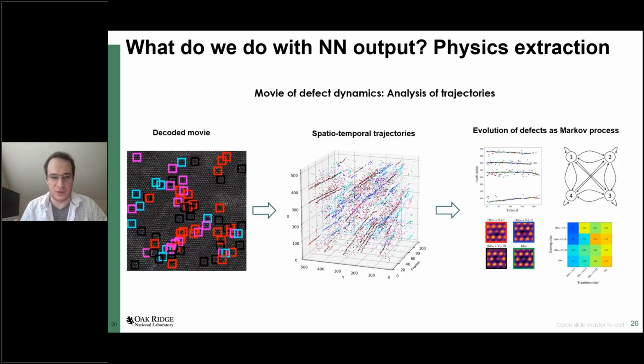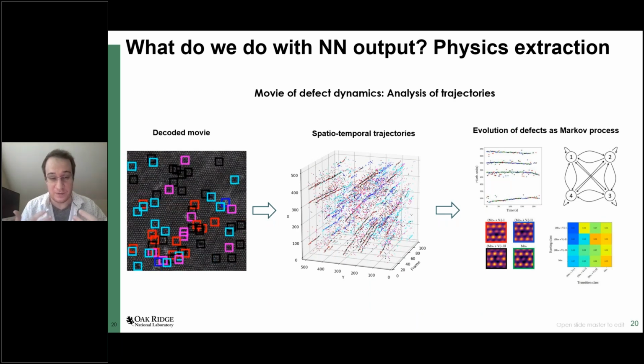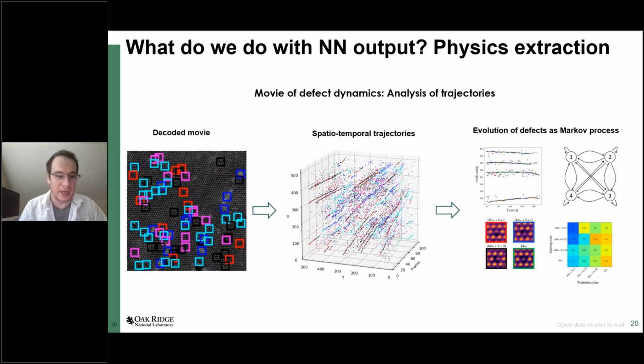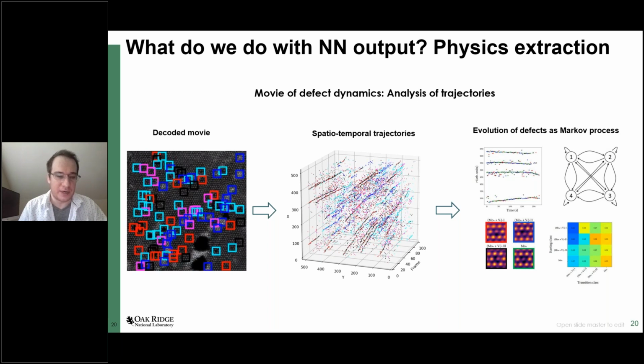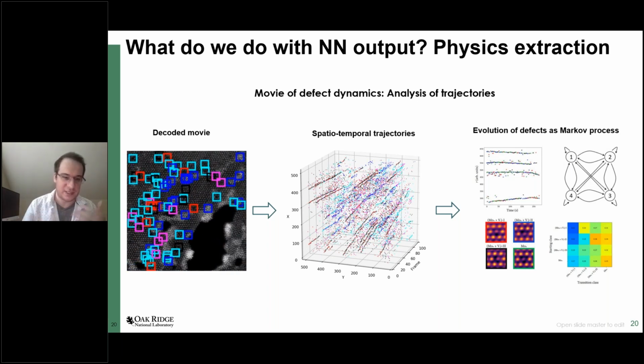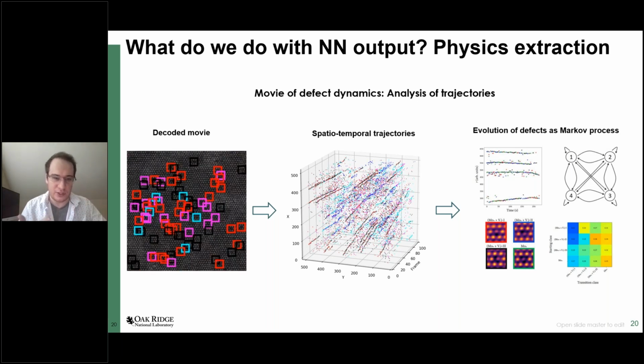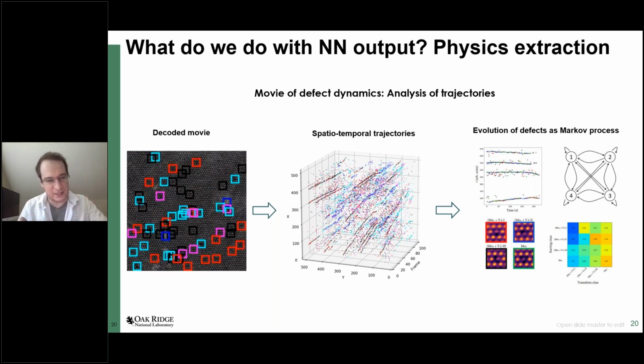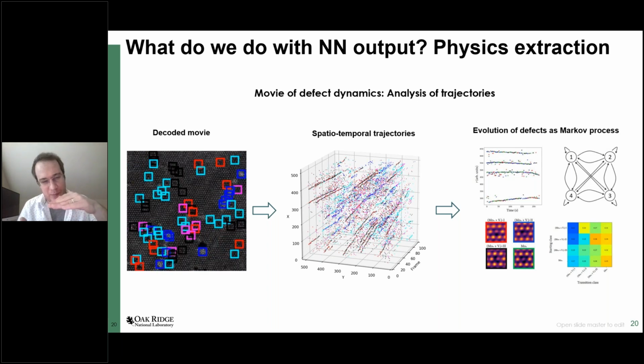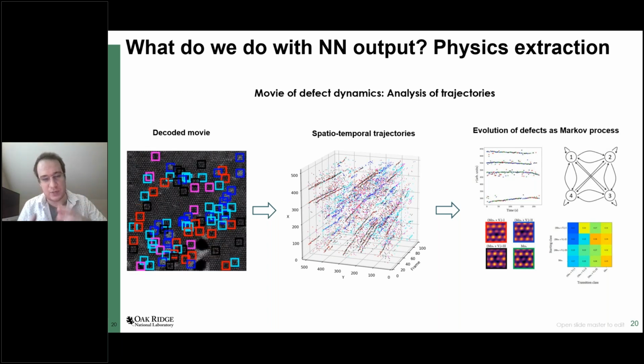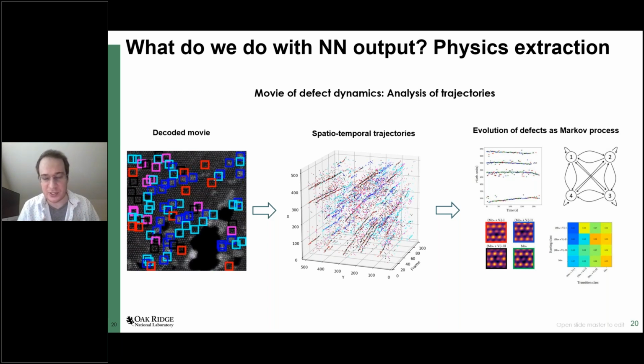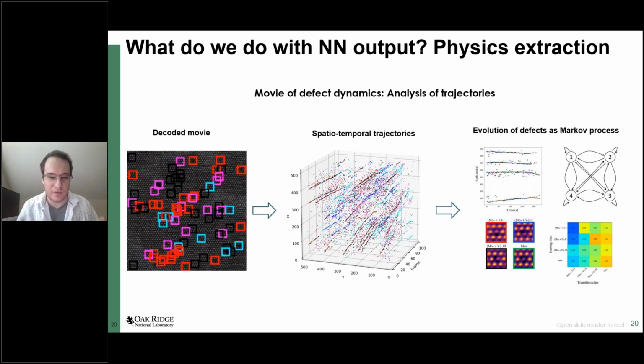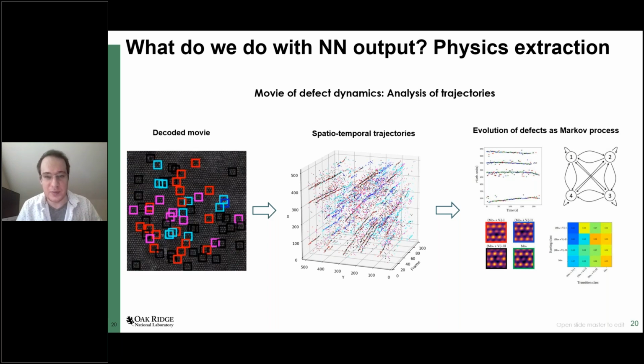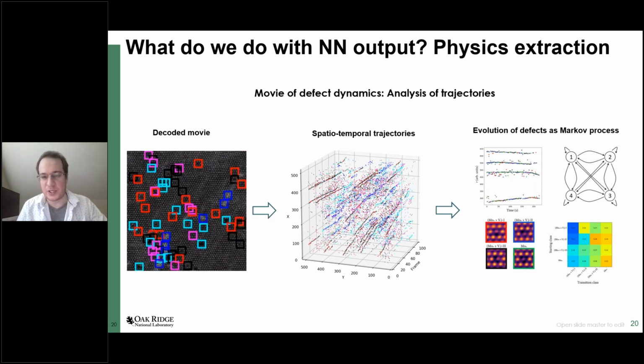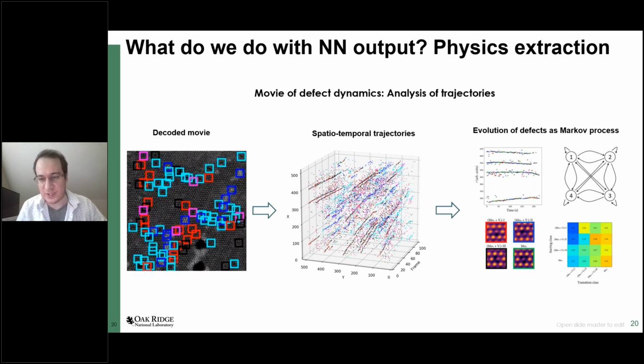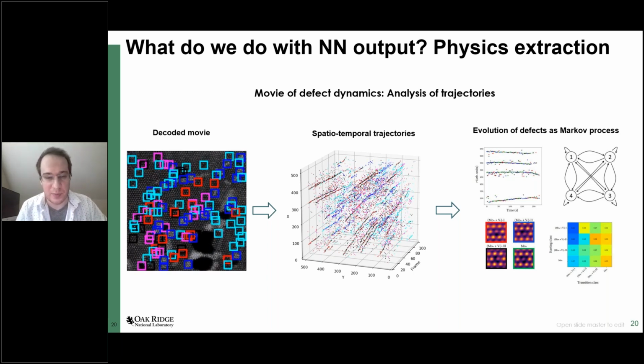Another example is we don't need to focus only on atoms. We can find different types of defects. Like in this case, we have a movie where defects are evolving in time, and we can use a deep neural network to convert this movie into the type and positions of all the defects, and we use that information to reconstruct a spatio-temporal trajectory. And then you can see that along some of these trajectories, defects switch between different classes. And so it is possible to describe the switching process as a simple Markov process and to calculate the associated transition probability measure.